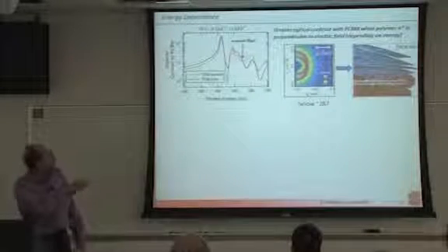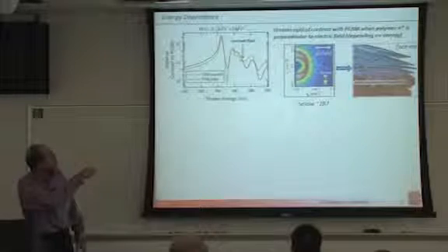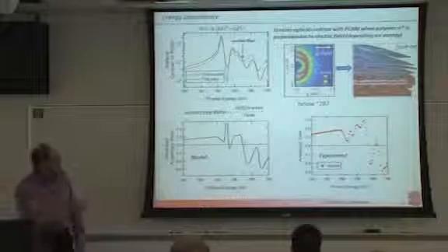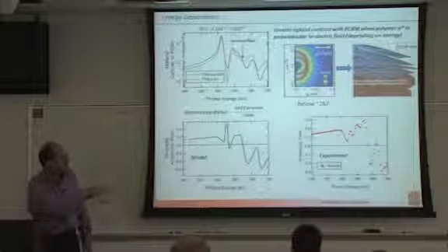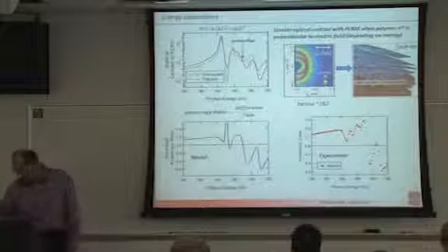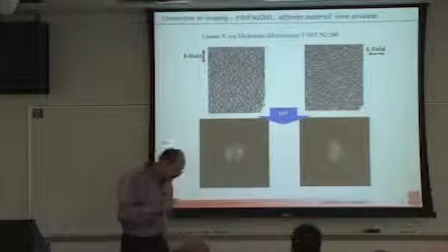We go through these optical constants, so we do the transition dipole moment perpendicular and parallel, the contrast flips here, and we can model this, and more or less we get the shape right, except for this spike. We get this right, and below the edge we can therefore sort of see what's going on.